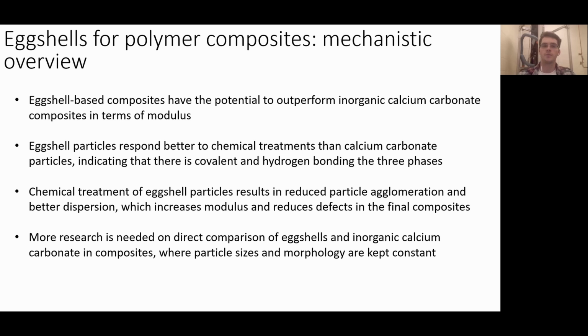So to kind of conclude, eggshell-based composites do have the potential to outperform inorganic calcium carbonate composites in terms of tensile modulus and tensile strength. And eggshells especially seem to respond better to these different kinds of chemical treatments, which the authors of the two papers I presented attribute to interaction between the chemical modifications and the proteins present on the eggshell surface, which is something that isn't there in inorganic calcium carbonate fillers. Again, these chemical treatments can also reduce particle agglomeration, promoting better dispersion, which will give you an increase in your mechanical properties and a reduction in defects.